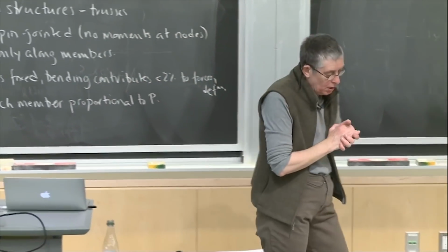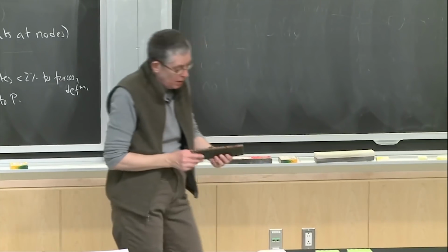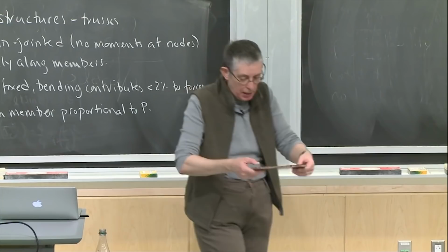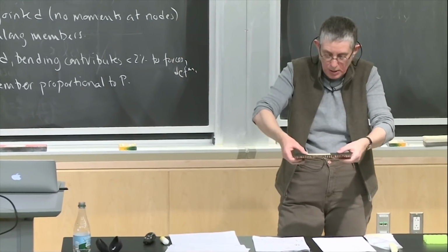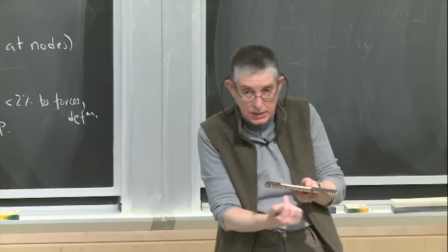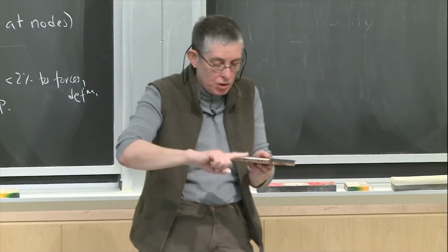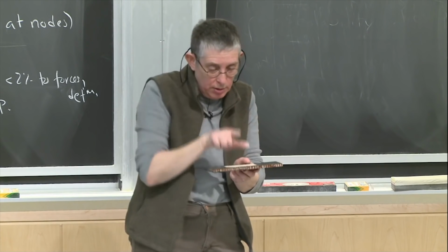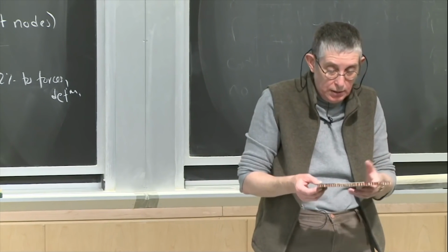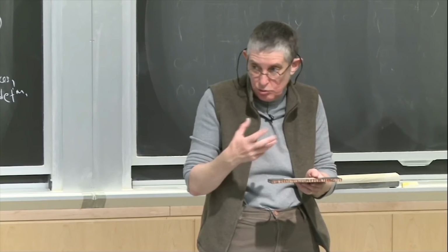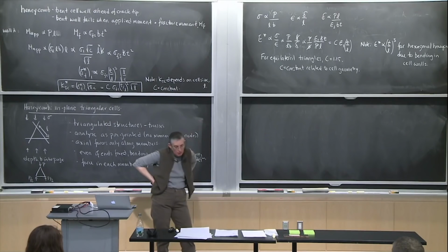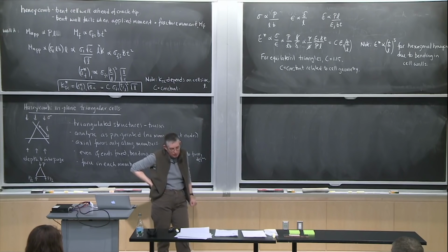The honeycombs are also, I should just back up a little bit. The honeycombs are used in sandwich panels, and when they're used in sandwich panels, so I brought a little panel in with carbon fiber faces and a Nomex core. If you bend that panel like that, you're going to get shear stresses in the core, and the shear stresses are going to be kind of going this way on, and that way on. And so those shear stresses are out of plane. They're sort of in the x1, x3, or x2, x3 planes. And so you need the out of plane properties for the shear properties in the sandwich panels.